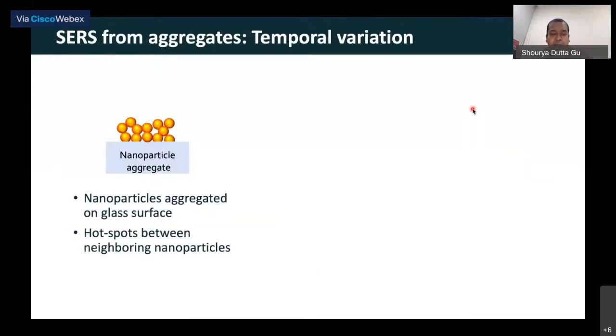Now, the simple system that you can do is you take these particles that we have synthesized. Now you basically make an aggregate by reducing or increasing the pH. Now, once you have these aggregates, between all these particles, you have the junctions which have a very small gap. Now, if you remember, if you reduce the gap, you have a high field. The same principle applies here. Right? So all these junctions will give you a high signal for Raman. And that is precisely what we use.